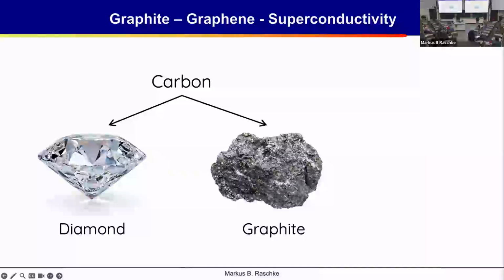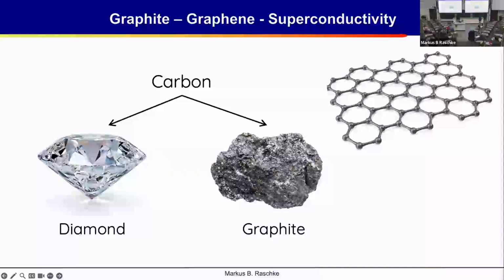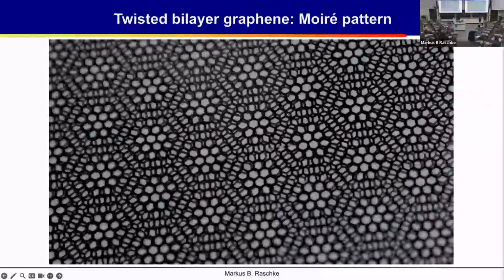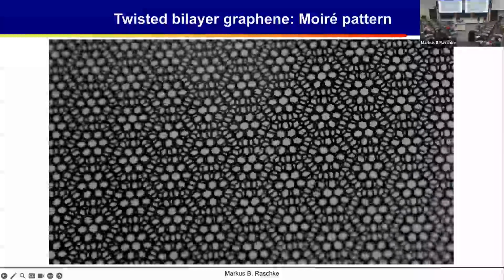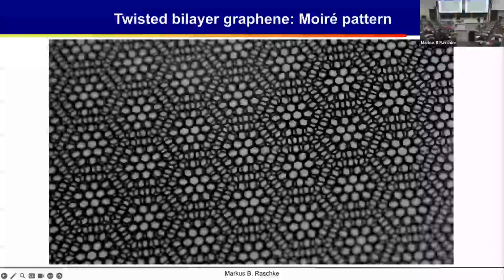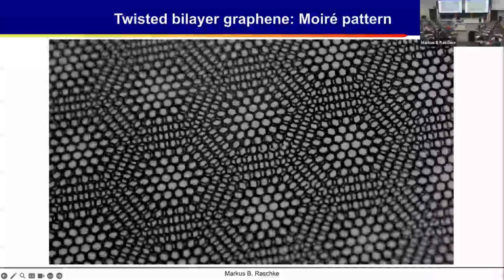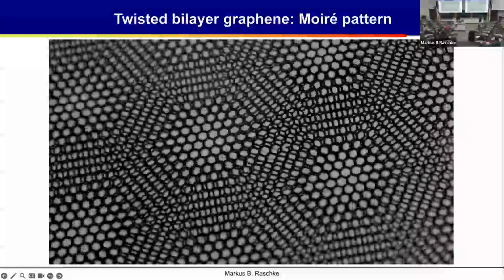Yeah, these are the two main different phases of carbon. One is where you have this hexagonal honeycomb pattern of the carbon arrangement, and then in diamond you have a three-dimensional arrangement. But what's fascinating is that this extremely simple structure of graphite in the single layer form, called graphene, actually allows you to generate quantum phenomena by something very unusual. This is when you take just two sheets of graphene and rotate the crystallographic orientation normal to that surface, you form, again, a beautiful pattern.